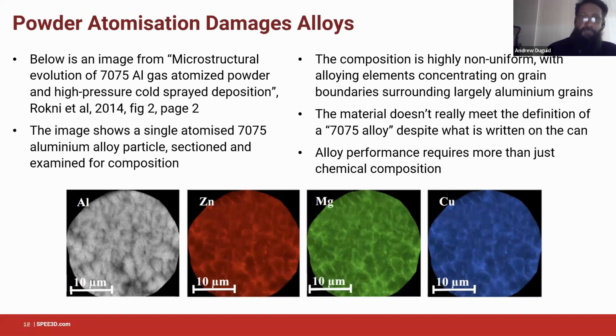So we've got a 7075 particle that's been gas atomized. And what we can see is that the alloy elements are really mal-distributed throughout that alloy. They're all present on the grain boundaries. No doubt they've formed all sorts of odd intermetallics. It's possible there's been some inadvertent hardening. The thermal hardening mechanism has actually operated inadvertently throughout the production of that powder.